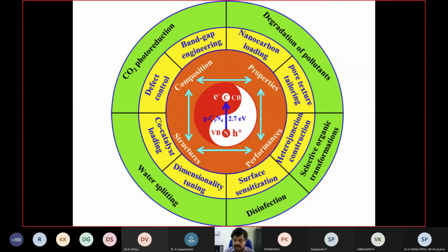But the problem is that the bare pristine graphitic carbon nitride has high charge recombination, so it will not show excellent performance. For that, you have to use several strategies to improve the performance of the material, especially band gap engineering. You can add some nanocarbon loading, make porous structures, form heterojunctions, surface sensitization, tune the dimension, add co-catalysts, and control defects. You can make composites or hybrid materials. You study the structure and physicochemical properties, then you improve the performance. Then that can be used for several solar energy related applications.